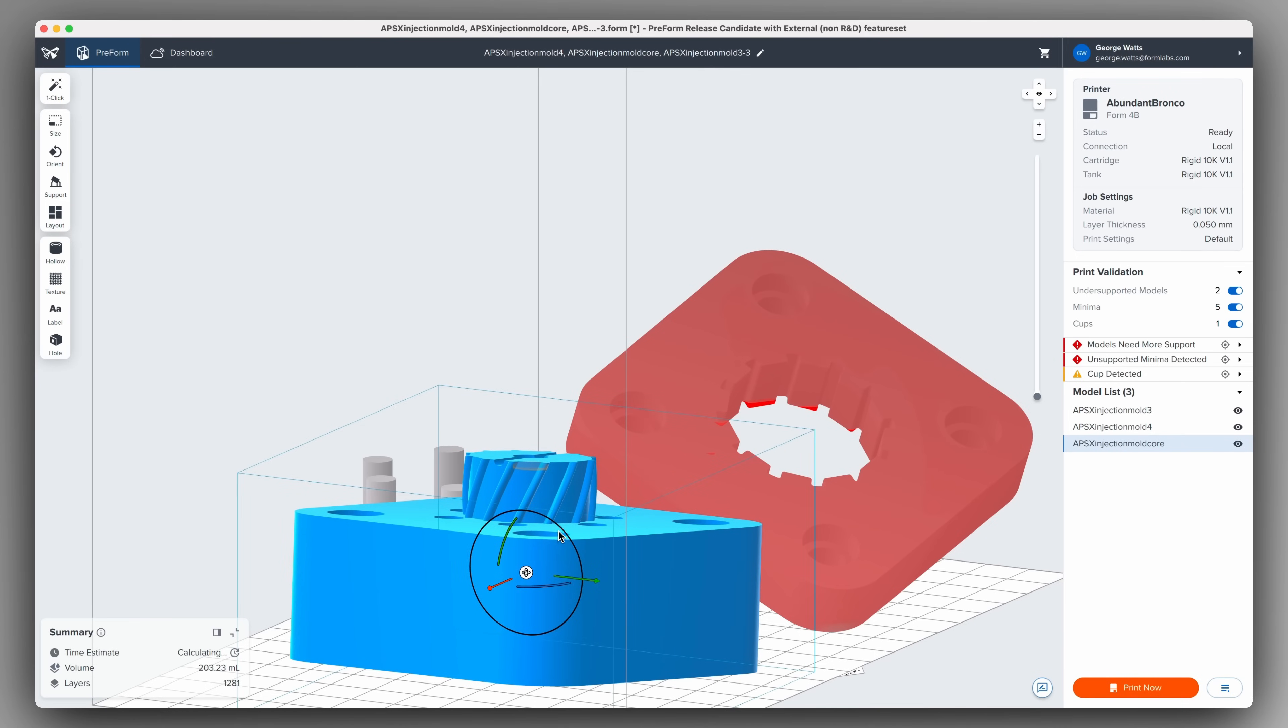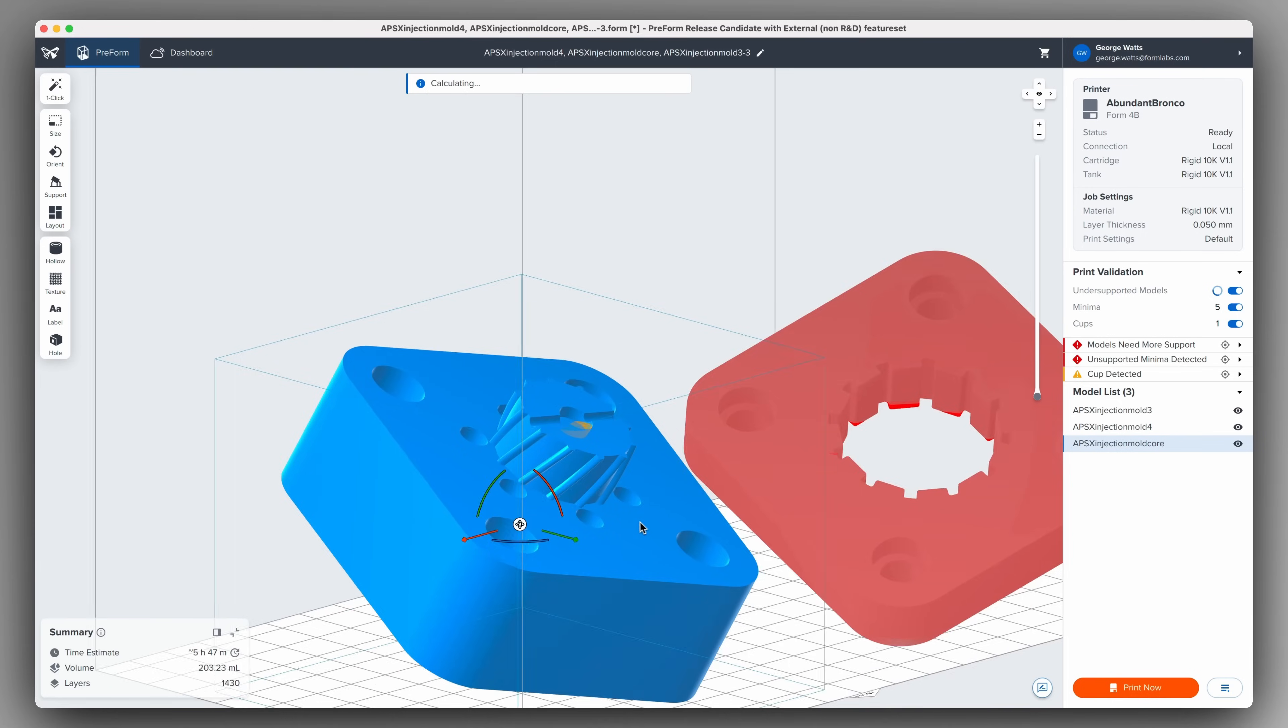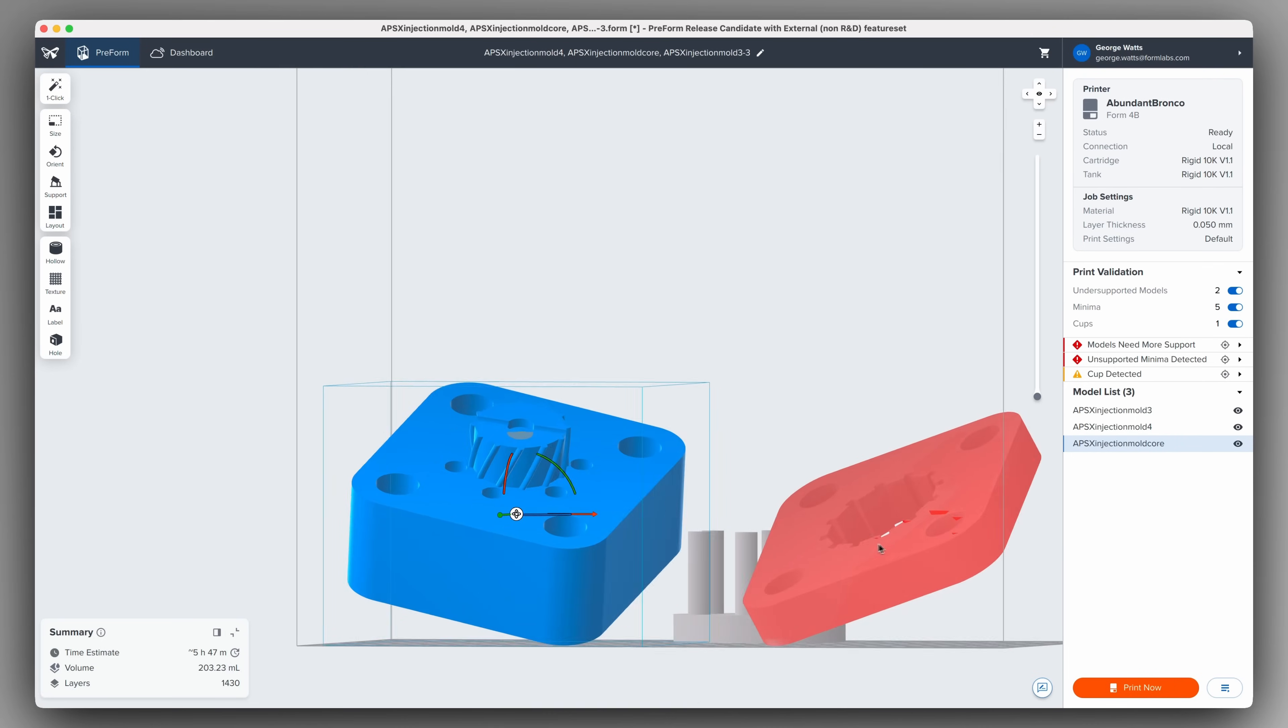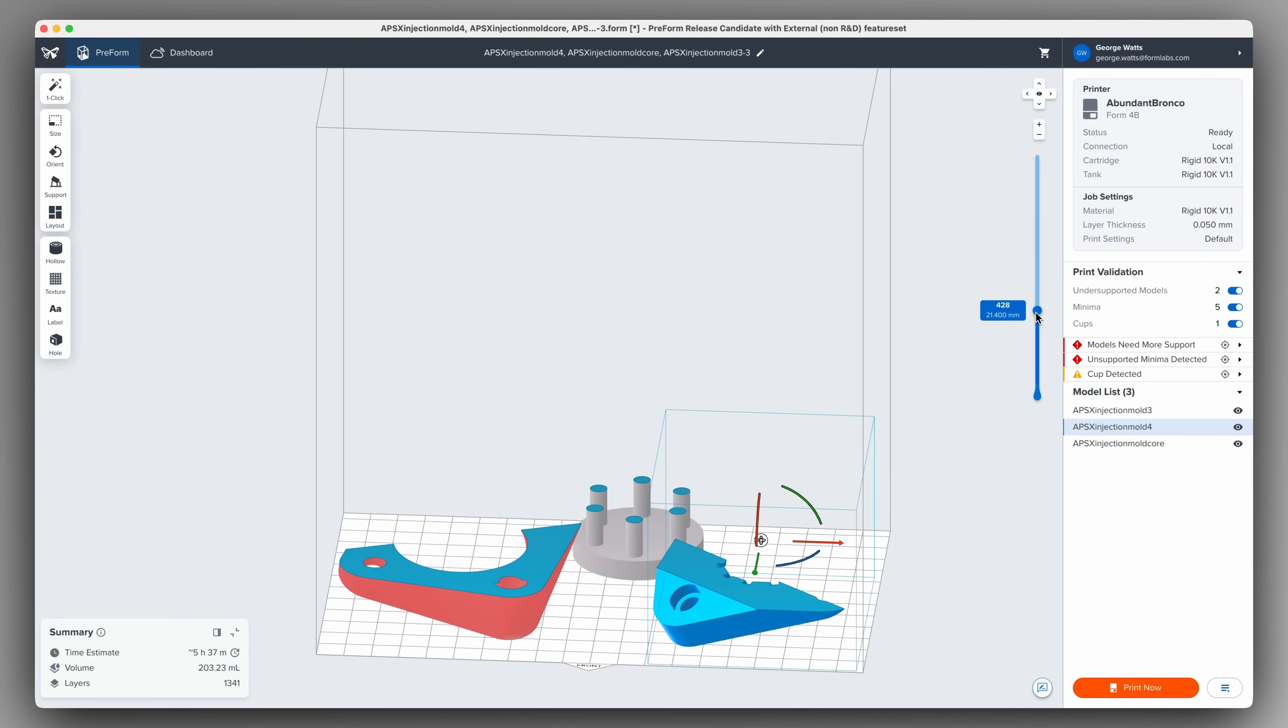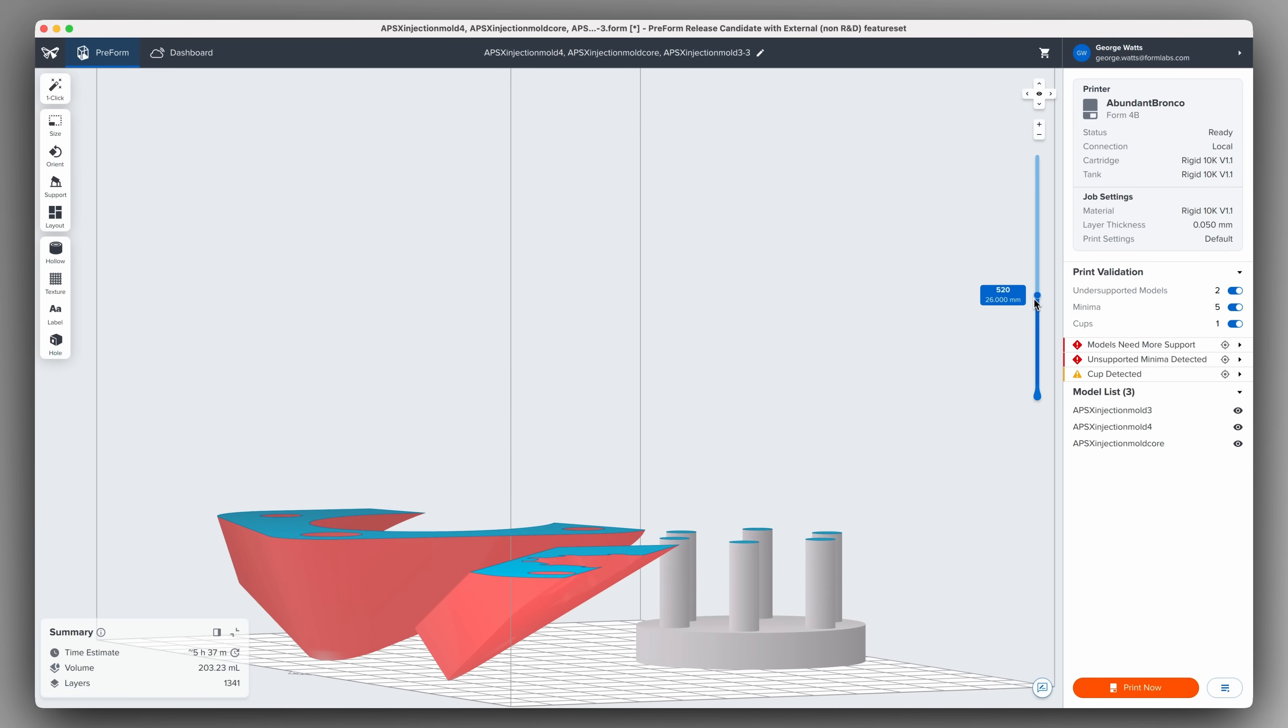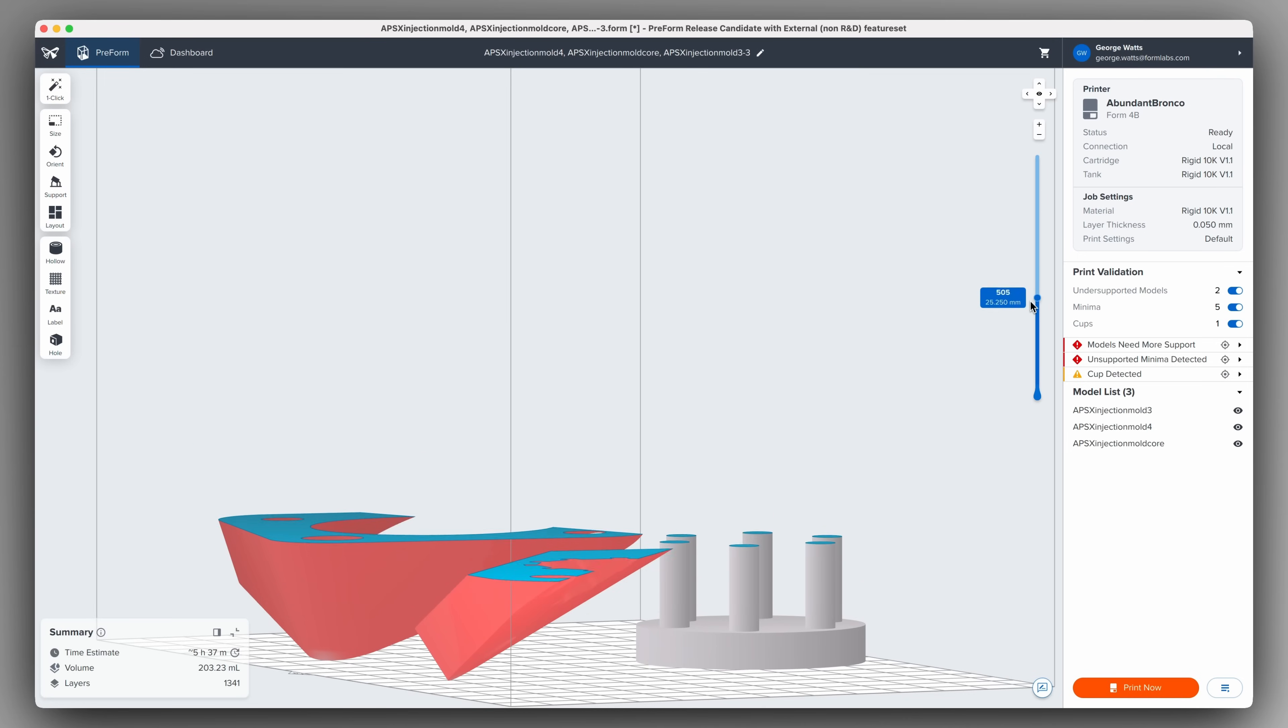Next, strategically orient your mold. Minimizing the amount of flat area in the XY plane will help reduce warping and curling of thin segments or large flat surfaces. So for these features, we recommend that the mold be tilted. For thicker and blockier models, this is less of a concern, especially in Rigid 10K. But here we show you an example of how you would angle your part. Angling your mold can also help minimize the amount of supports needed on critical mold surfaces.